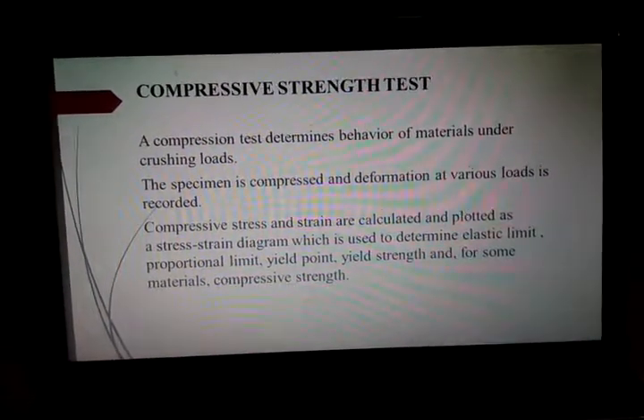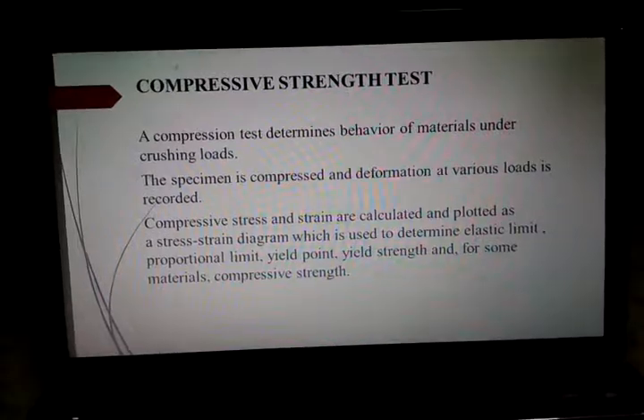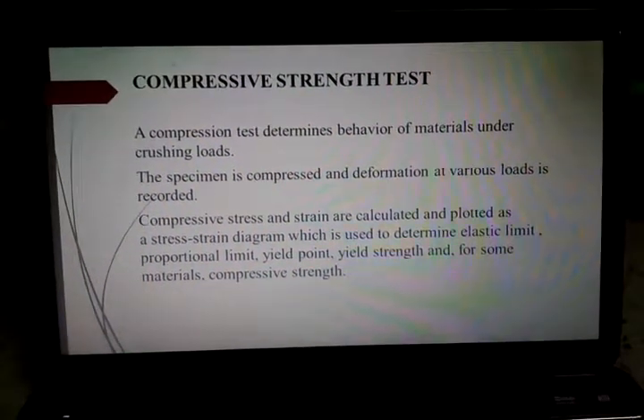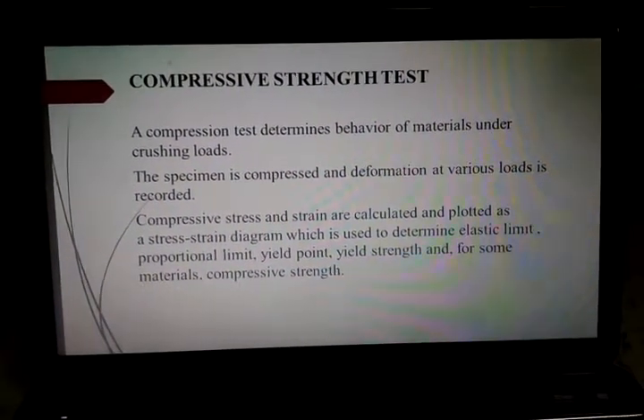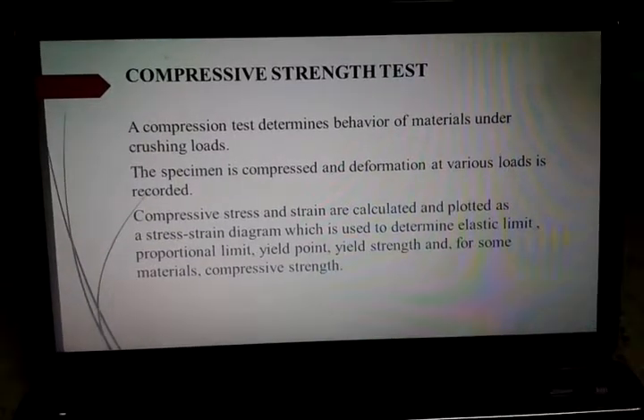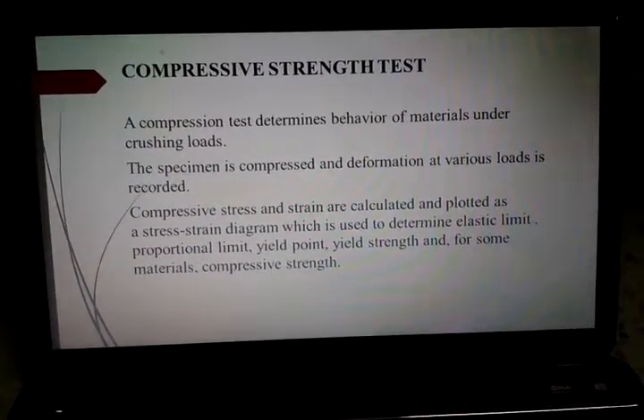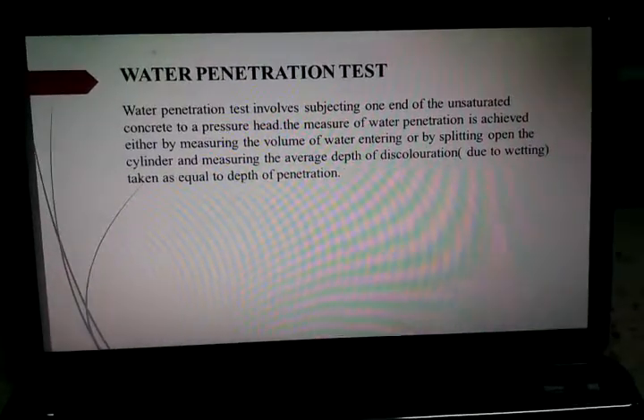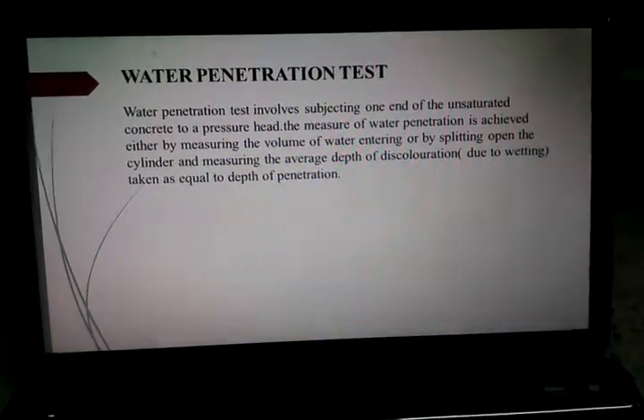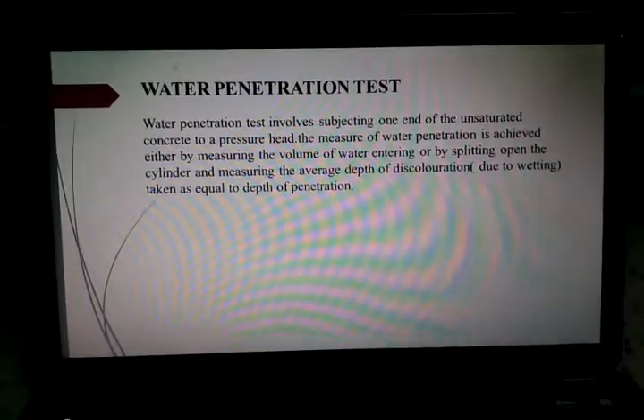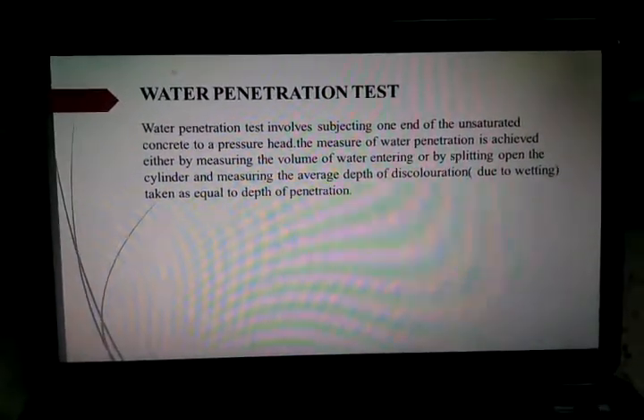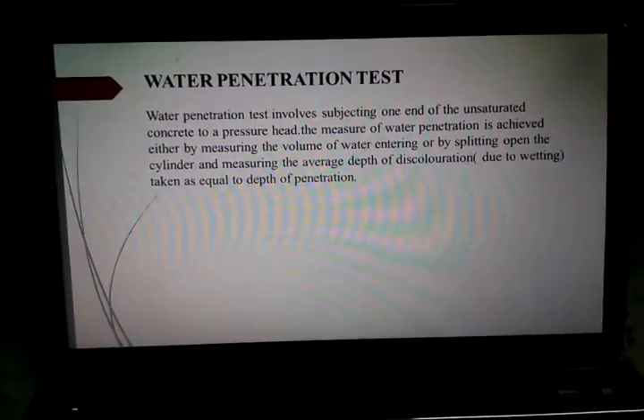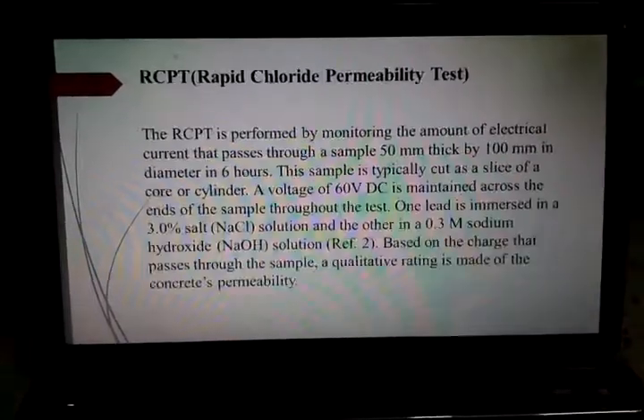Compressive strength test. A compression test determines the behavior of materials under crushing loads. The specimen is compressed and deformation at various loads is recorded. Usually a cube of size 150 by 150 is used. Water penetration test. Water penetration test involves subjecting one end of the unsaturated concrete to a pressure head. The measuring of the water penetration is achieved either by measuring the volume of water entering or by split opening the cylinder and measuring the average depth of discoloration due to wetting taken as equal to the depth of penetration.